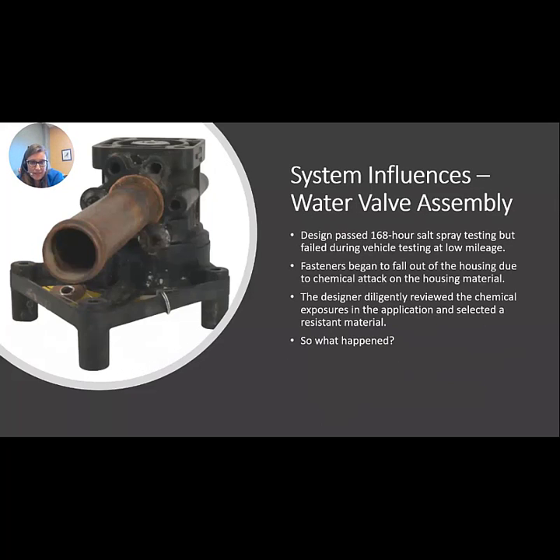So the design passed the required salt spray testing, but when they put them on for vehicle testing, they started showing failures at low mileage. So what happened was, you can kind of see it on this picture here, we've got fasteners that are falling out. So this fastener fell out and allows this copper pipe basically to loosen up from the body, and it allows leakage of the fluid. And we've got some corrosion products on this one. This one you can't see very well. But the designer diligently reviewed the chemical resistance requirements. So this shouldn't have happened.